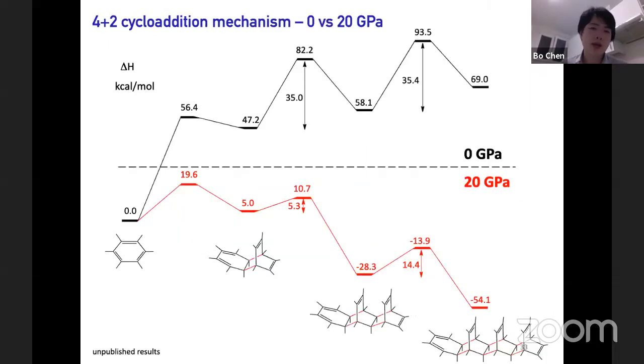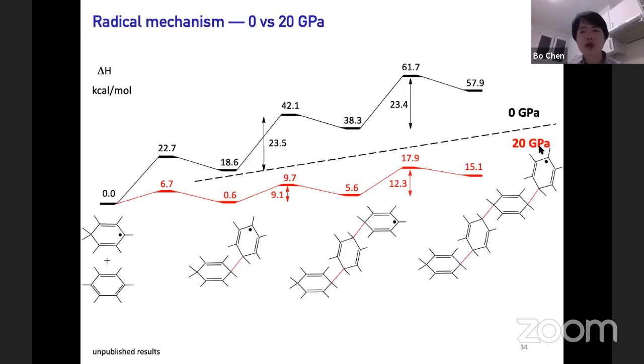So with this method, we are able to calculate the reaction barriers and reaction pathways for the 4+2 cycloaddition and the radical pathway. Here we are looking at the 4+2 cycloaddition, starting from benzene, going through a transition state to a dimer, then another transition state, trimer, and so on. We can see that pressure really stabilizes this pathway. The reaction at 20 GPa becomes exothermic, and the overall barrier is reasonable, 19.6 kcal/mol. It's reasonable for a room temperature reaction. On the other hand, for the radical mechanism, even at 20 GPa, the reaction is still endothermic, and that means the reaction is not favorable under pressure.